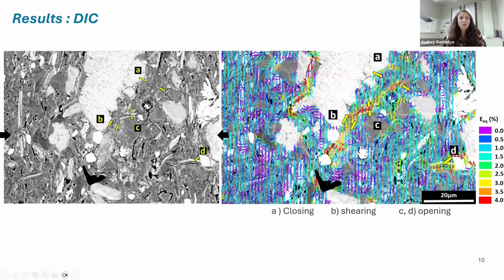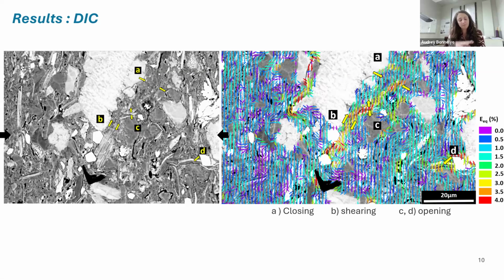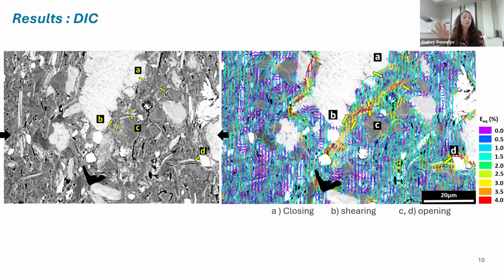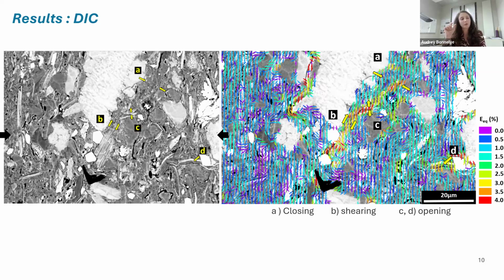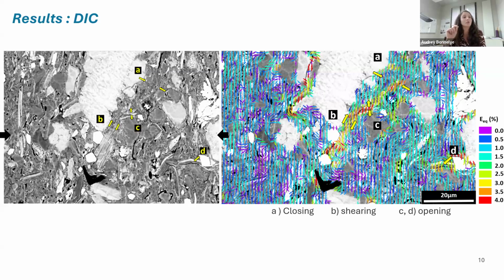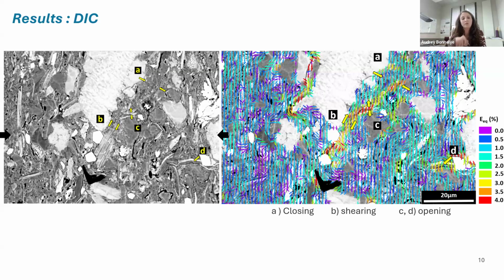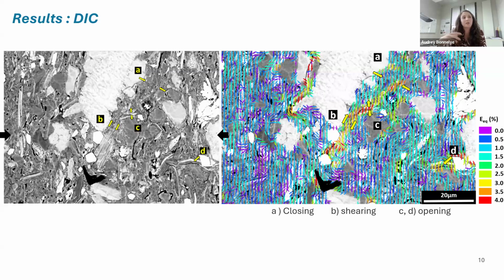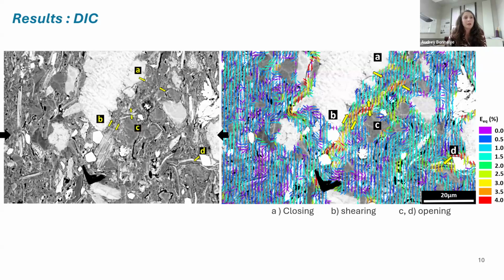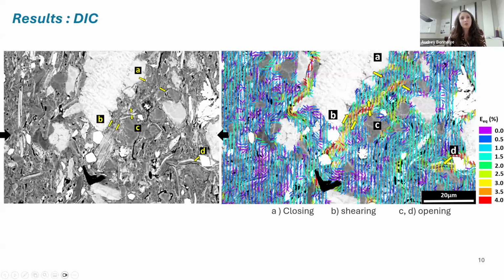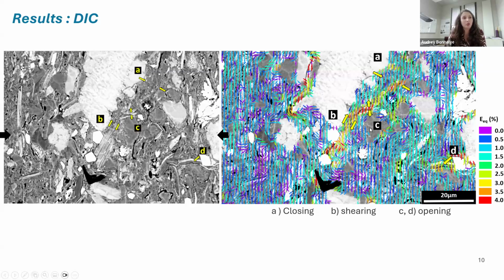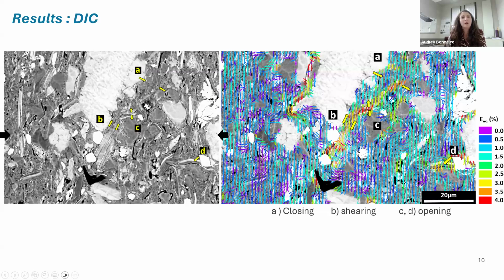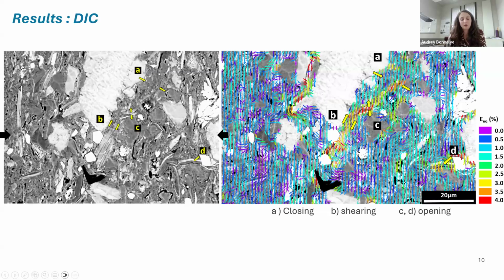Then once we have those images, we do the digital image correlation. It consists of making a sort of virtual grid on your screen, taking some correlation domains that are squares of the pictures, and then looking in the deformed image for the position of the same square in the initial image. From that, you can calculate the displacement of that square, and this gives you the full displacement field, which is shown here, transformed first into equivalent deformation, and shown on the picture on the right, where you can see with the color map the equivalent deformation of the matrix in your sample.